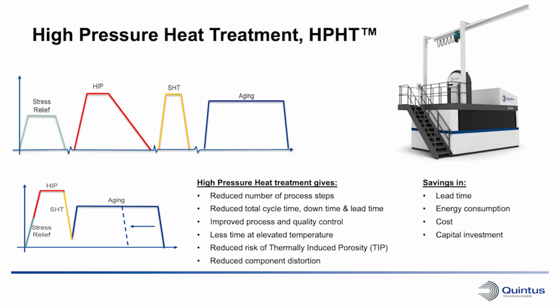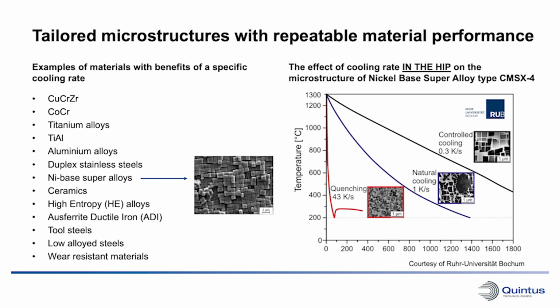Okay, cool. I know Quintus calls it high pressure heat treatment. You're doing lots of different steps here. So what kind of materials are you doing solutionizing steps on? Well, mainly it's on nickel-based superalloys. They require a solutionizing step, but that only requires a specific cooling rate, or above a specific cooling rate, when the parts have been above a certain temperature. Okay. And since the HIP temperature is above that, and if we can cool with a sufficient cooling rate, we can combine the HIP and the solutionizing step.